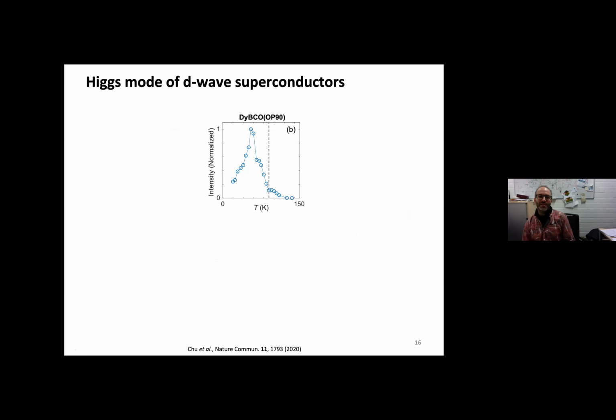And if we look at this now, for example, here for the optimally doped LSCO, then we see here below TC, this is the black dashed line here, we see a strong onset of these third harmonic generation as we've expected. And yeah, now on the first view, this might look like, oh, there is a very sharp resonance in the system. However, what we have to take into account here is, of course, as soon as the sample becomes superconducting, then also a huge screening sets in. So we have to correct this third harmonic generation with respect to really the local field that is in the superconductor itself.